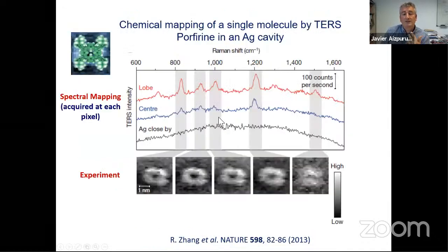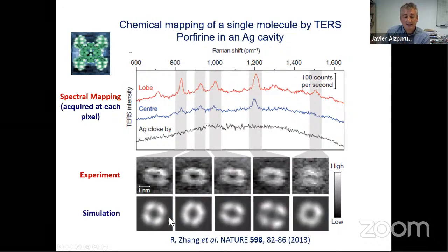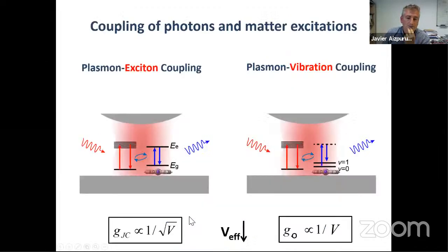So now, with this confinement at the pico cavity level, we can try to reproduce these Raman experiments and see how, in the simulation, with this pico cavity scanning the molecule, we can recover for every single vibrational fingerprint the level of resolution obtained experimentally. This is a proof that the pico cavity in the tunneling junction, a few, 1, 2, 3 atoms in the tip of a tunneling junction, are mapping with a resolution which is close to the electronic current resolution, okay?